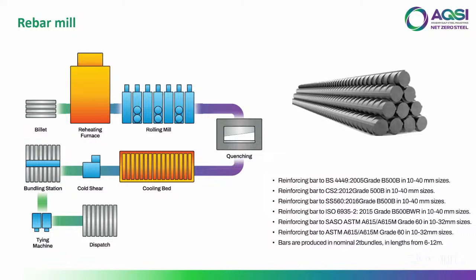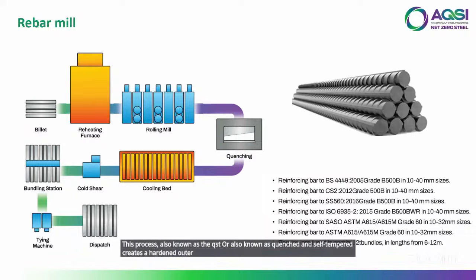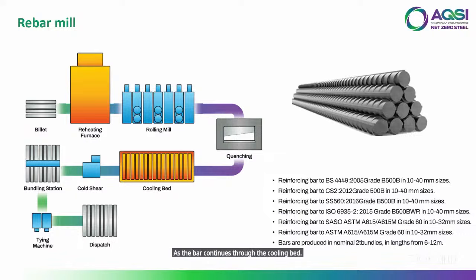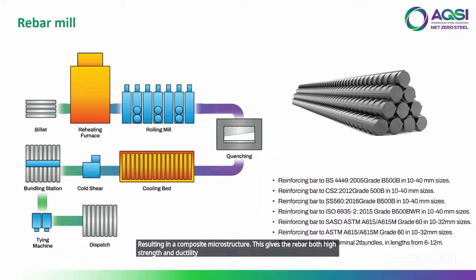Immediately after the last rolling pass, the hot bar enters the quenching box, where high pressure water jets cool the surface rapidly. This process, also known as QST, or quenched and self-tempered, creates a hardened outer shell while the core remains hot. As the bar continues through the cooling bed, the retained heat in the core tempers the outer layer, resulting in a composite microstructure. This gives the rebar both high strength and ductility, ideal for seismic performance and crack resistance.